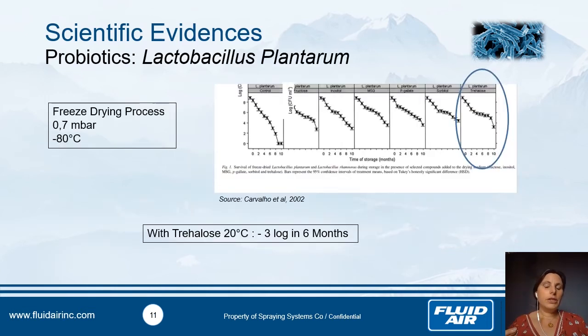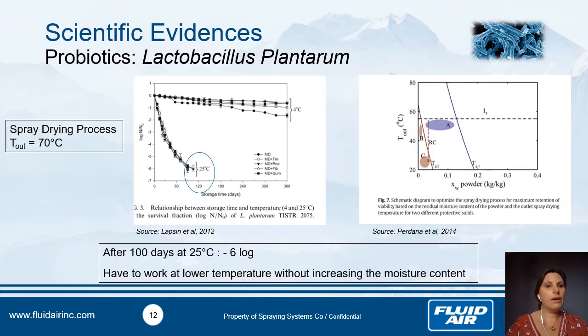To have a good comparison, we did some literature research, and with freeze drying using trehalose, we observe that they have a loss of 3 logs in 6 months during a stability at 20 degrees C. In case of the spray drying process, it's also interesting to compare with outlet temperature at 70 degrees C. After 100 days at 25 degrees, they lost 6 logs, so it's a lot.